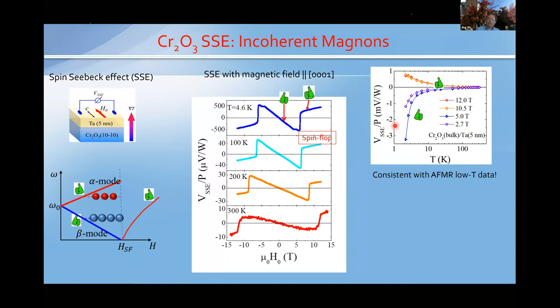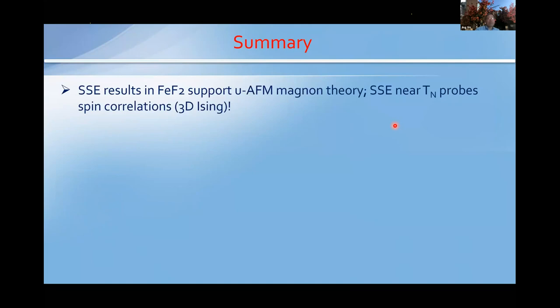So my time is up. Let me just quickly summarize. In the uniaxial antiferromagnetic material, we picked iron fluoride, which has a very strong spin flop transition. I showed there's still a magnon contribution to the spin Seebeck effect, which has a characteristic peak that is expected from this two-magnon type of picture, right?